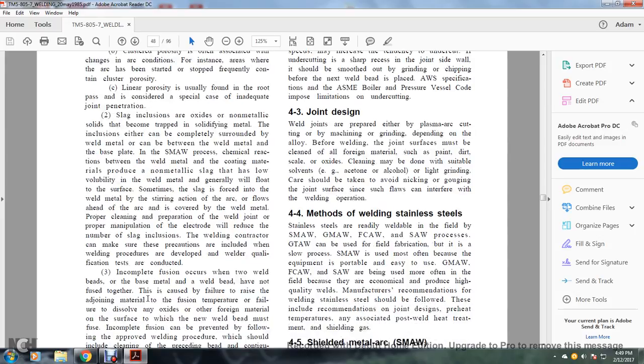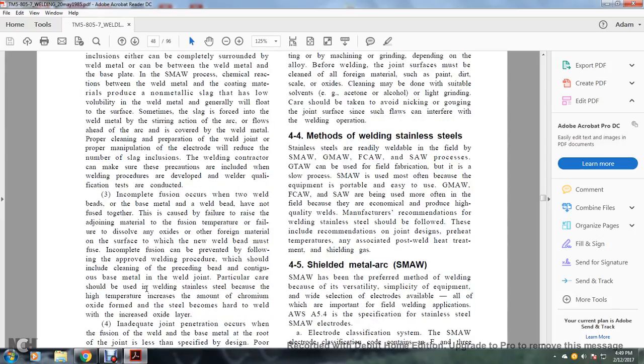Inclusion of slag in welds can be avoided by the main precautions included in the welding procedures that are developed when welder qualification tests are conducted. 3. Incomplete fusion occurs when the weld bead and the base metal, or two weld beads, have not been fused together. The cause is failure to raise the adjoining material to fusion temperature, or failure to dissolve any oxides or other foreign material on the surface to which the new weld bead must be fused.